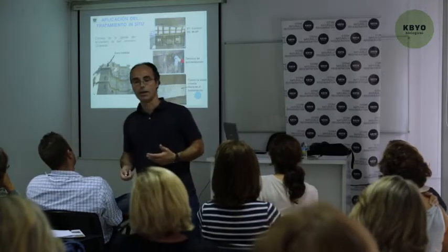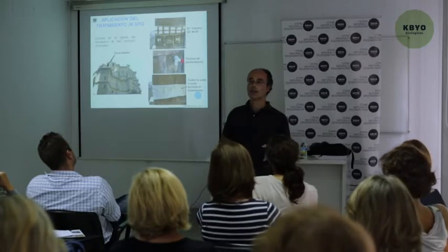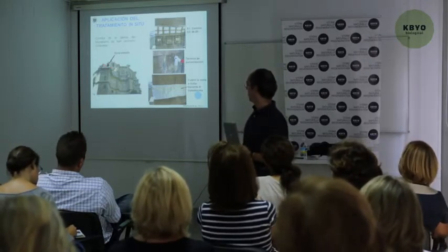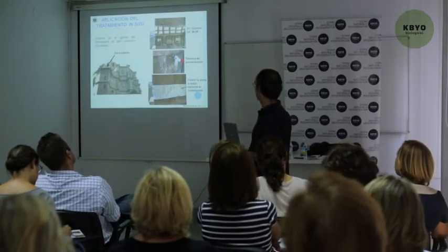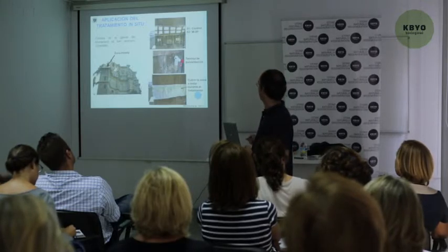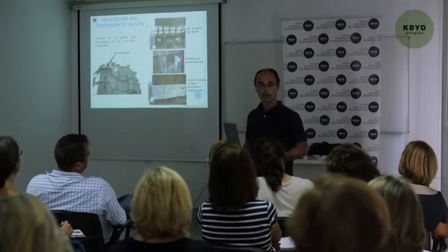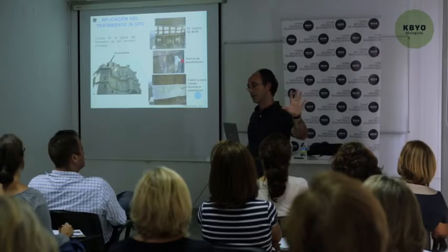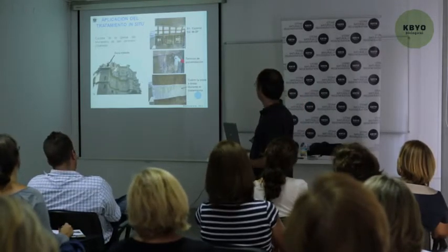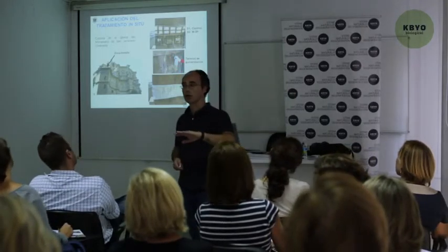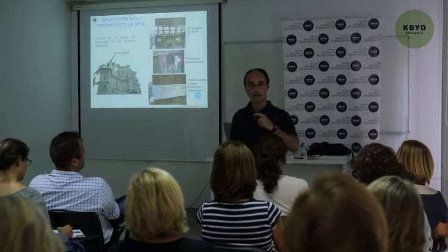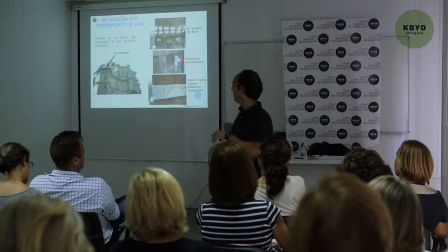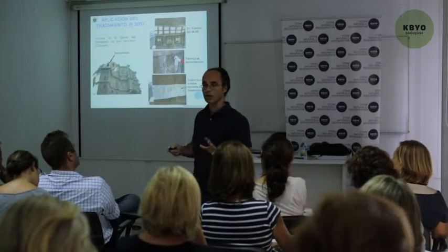How can we see or evaluate the consolidation carried out by those bacteria? Here we see the sample of sandy limestone before and after the treatment. In this case, we have used the technique of electron microscopy. This technique shows in detail the microtexture. We can notice here pores and crystals of calcium carbonate before the material treatment, a very cohesiveless and sandy material. And after the treatment, we see a whole material that recovers the stones and leaves pores opening. We also see cell remains of these bacteria. Everything else is calcium carbonate.